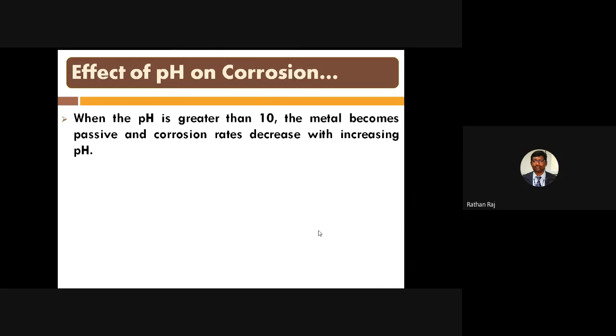Due to carbonation, or the use of sodium chloride for ice breaking, or chloride ions in coastal regions, the pH level can drop significantly, affecting the steel, and then the corrosion starts. A higher pH means there are fewer free hydrogen ions. Low pH clearly accelerates the corrosion by providing a plentiful supply of hydrogen ions.